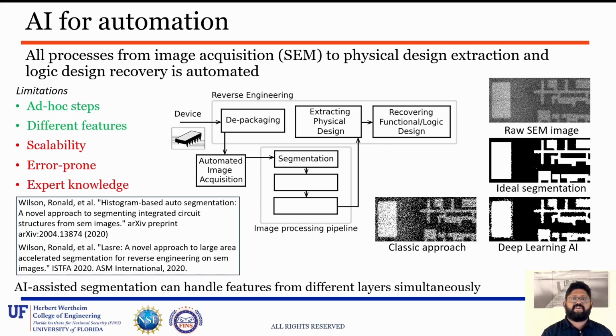The first method, called histogram-based automated segmentation, relied on approximating pixel intensity distributions for material to perform segmentation. The second method leveraged noise in the SEM image to bound areas in the image with constant noise signature. In simpler terms, it used texture to segment the image automatically. The added knowledge on the statistics of the image helped automate the segmentation process without ground truth labels.